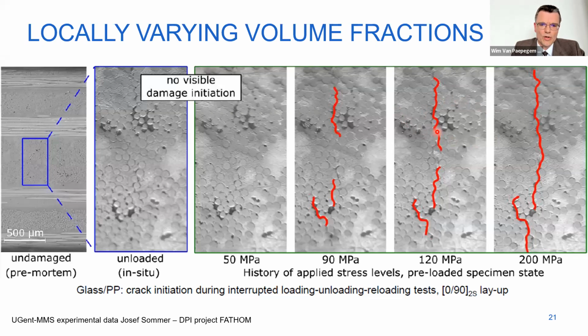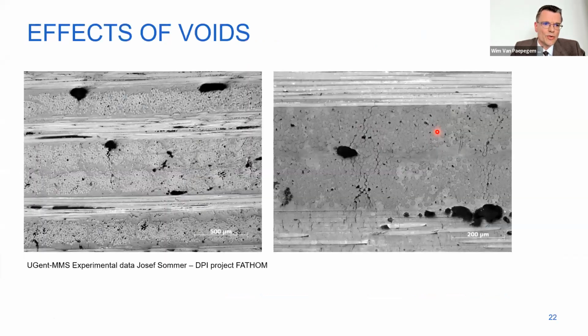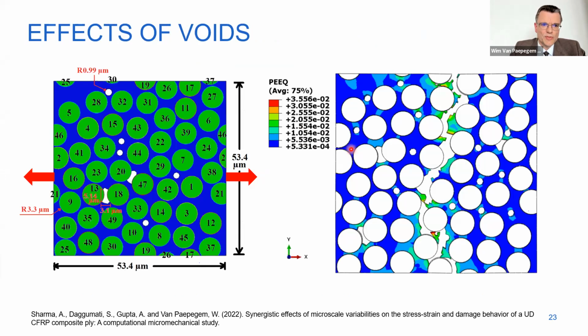than what you assumed maybe in your RVE. And another thing is voids. Sometimes when we get industrially produced laminates with quite low consolidation pressure, you can also see voids in the laminate. And also these can sometimes be a start of cracks. Those you can also include in your RVE by assuming a certain void content. And of course, obviously, these will often be initiation sites of damage and also reduce the transverse tensile strength.